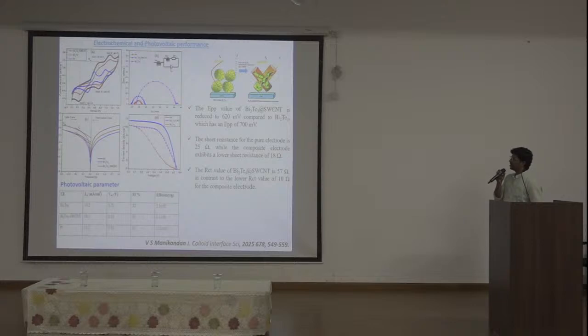SWCNT, the charge transfer resistance is reducing. The blue color curve shows that the charge transfer resistance is highly reduced, and the series resistance of the electrode also reduces after inclusion of the CNT. There is no change in the short circuit current density as well as the open circuit voltage. The short circuit current density indicates the light harvesting, and it does not change because in all the devices we are using only TiO2 as the photoanode material. The light harvesting efficiency does not change, but only the fill factor of the material changes.